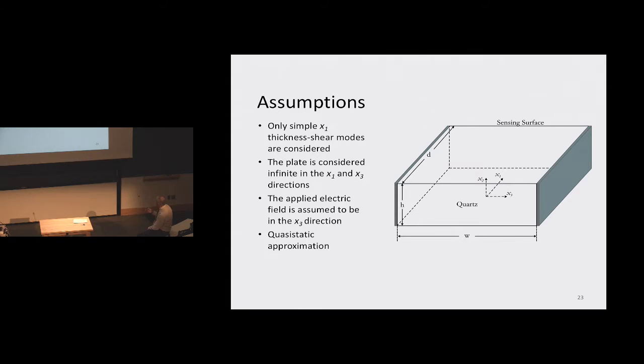The assumptions we made: only simple thickness shear modes are considered. Displacements are transverse to the direction of propagation, which is in the x2 direction. Displacements are in the x1 direction. The plate is considered to be infinite in the x1 and x3 directions. The applied electric field is in the x3 direction, a lateral applied electric field. And we use the quasi-static approximation.